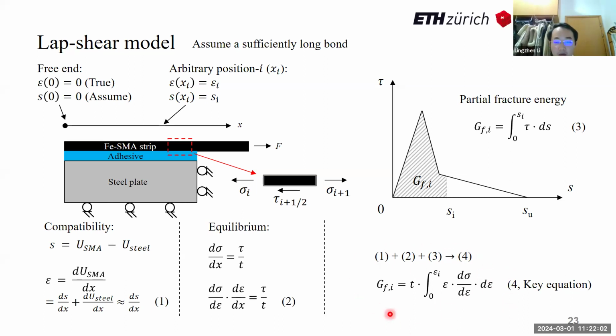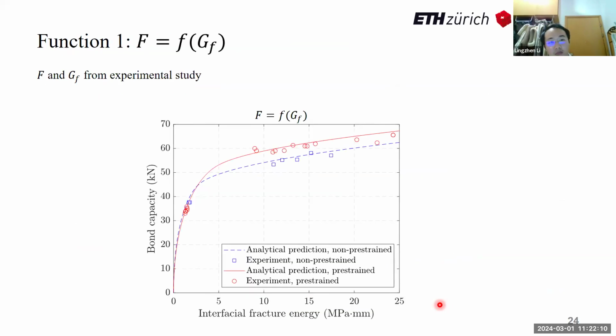Further deriving this model a bit, we would have several practical functions. Due to time limitation, I won't go deep into details, but will show you some of the key results. The first function is a prediction of the bond capacity. The two curves are my model prediction: the solid red for the bonded joint with pre-strained SMA, the blue curve with non-pre-strained SMA. The dots are my experimentally measured results. We see that the experimental results are distributed around my model prediction.